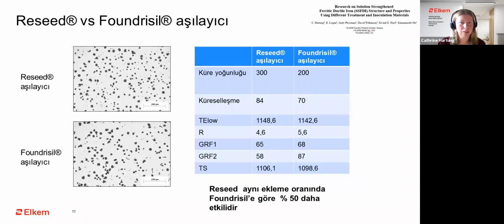Next. So we go to an example in ductile iron and look at the difference in performance of Reseed and Foundrisil. Foundrisil is a calcium barium inoculant, which can be used for both gray and ductile iron, while Reseed is a cerium-containing inoculant specifically developed for ductile iron, and especially ductile iron treated with pure magnesium or where there is low sulfur and oxygen after the treatment. So where you have a high need of an inoculant and a good performance of the inoculant.